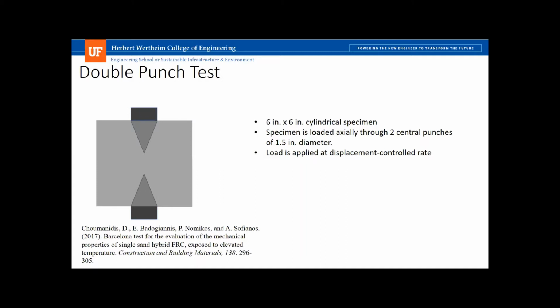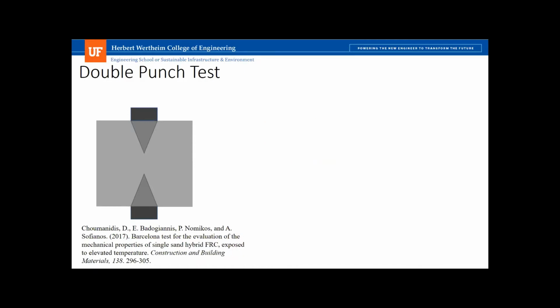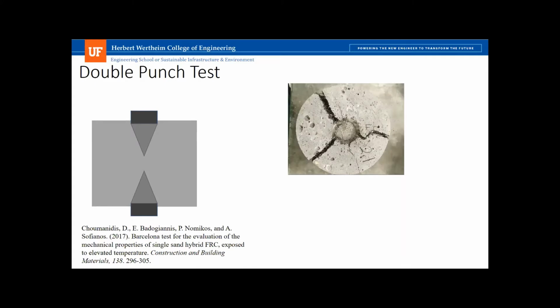And then when you put it in compression, you get cones of failure that form underneath those punches. As you continue to compress the punches together, the punches come inwards, and because of wedging action of those cones, it forces the concrete outwards. Okay, so when it does this, you get a failure as shown. Since ultra high performance concrete is fiber reinforced, you do get multiple cracks there because you're able to distribute the cracks. That's what you want to see.